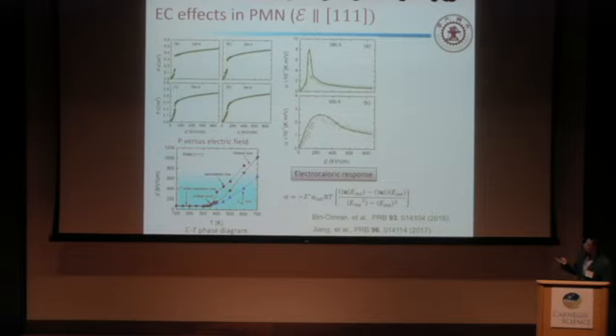From the picture, we can see that we find a giant EC response at intermediate electric field. The magnitude of the electrocaloric coefficient agrees with the experiment. In other words, we also find a giant electrocaloric response near the critical point, just near the first order transition. But at higher temperature, we also find this value is bigger. In other words, in PMN, near the critical point, we find a giant electrocaloric response, but higher temperature also has a bigger electrocaloric response.